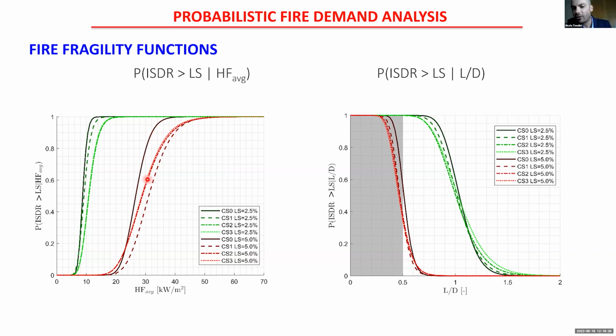Whereas when we introduce the uncertainty in the steel yield strength, the probability of exceedance of the limit state is lower. And then of course, if we consider more uncertain parameters, this probability of exceeding is lower. So here, for example, case study 2 and case study 3, most of the times provide the lower probability of exceedance of the limit state. And then also it can be used.